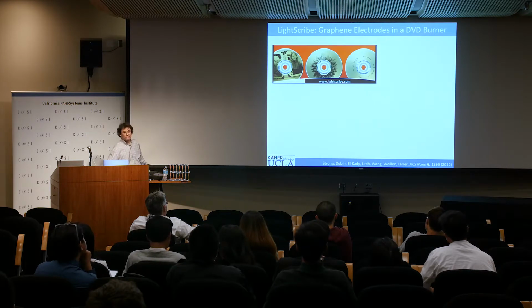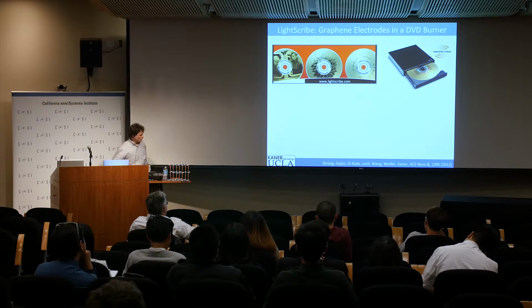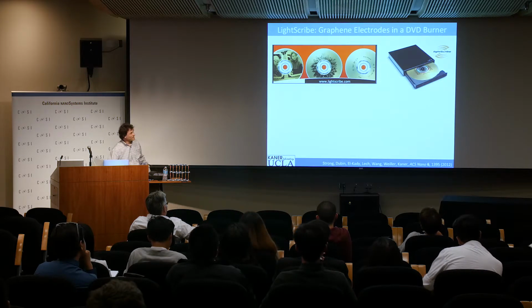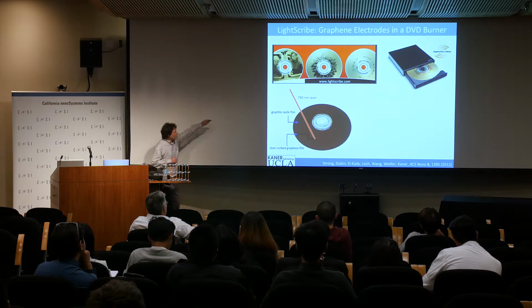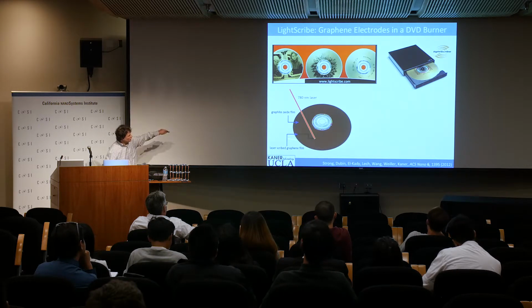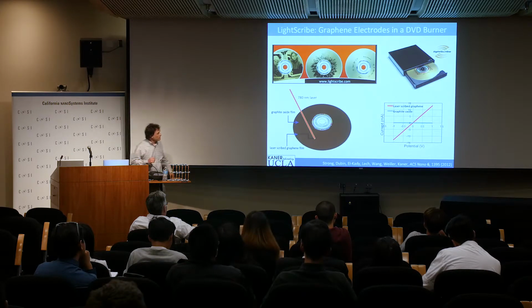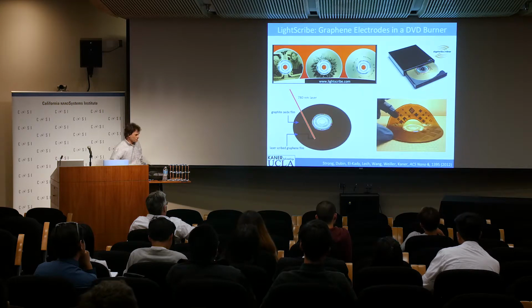And so this is something you may have gotten. It costs $25. You get it for your computer stack, and it's used to label CD disks. And so what we did is we told it to run this laser across, and we turned graphite oxide, which we put on the surface of the CD, into graphene. And you'll see we go from an insulator to a conductor. This is the current voltage curve. And here's what it looks like.